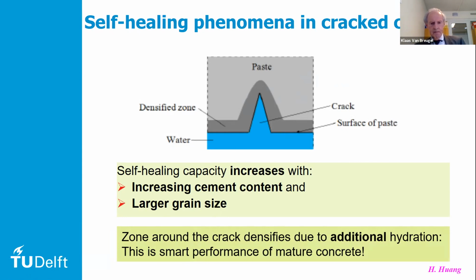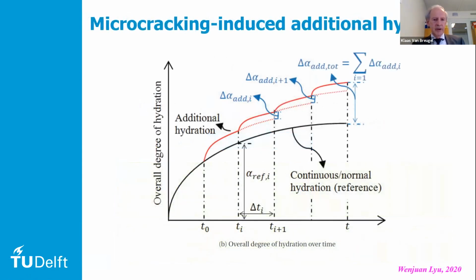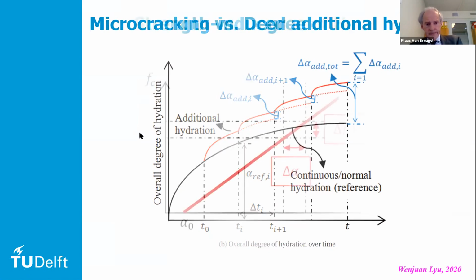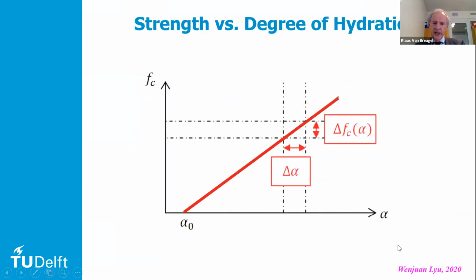Suppose now that this is something that happens always, that you have close to a crack some extra hydration, and we looked at a sample where you have multiple cracking, and when a crack occurs, then you see a little bit of extra hydration, and another crack, a little bit of extra hydration, and so on and so on. So then it might become stronger. We know that there is a good relationship between the degree of hydration alpha and the strength. And if there is extra hydration, then you can expect there will be extra strength.